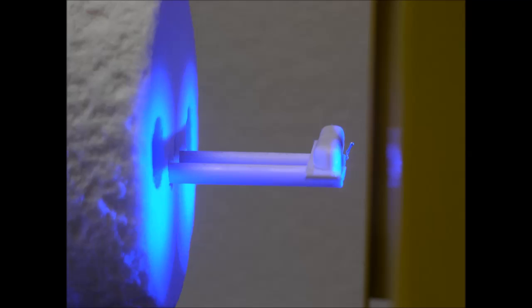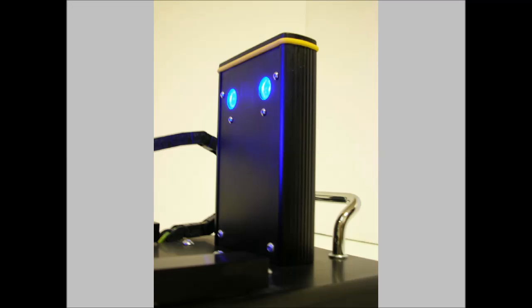Misura LT can be supplied with a heating rate up to 30 degrees per minute and up to a maximum temperature of 1380 degrees centigrade. The two ends of the sample are lighted by two beams of blue light with a wavelength of 478 nanometers. This light, with a very short wavelength, enables to reach the optical resolution of 0.5 microns per each pixel.